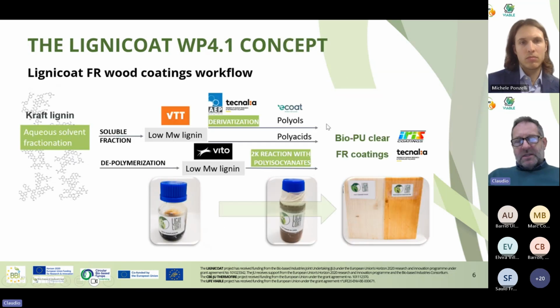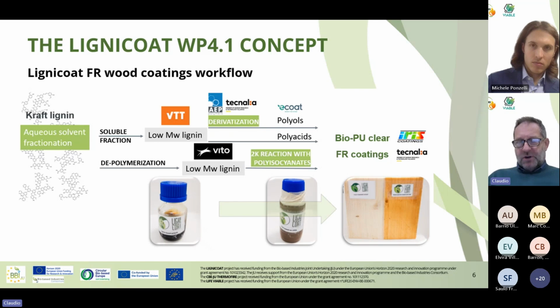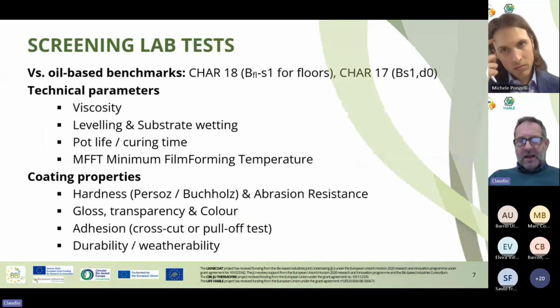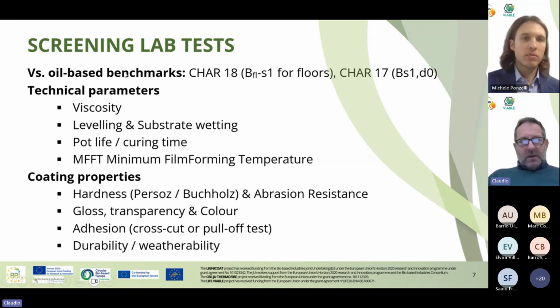Two-pack system means that lignin is included in one of the components and the isocyanate in the other, and you have two drums that will be mixed just before application, and the reaction occurs during application, and this is giving a particularly high characteristic of the coating. We have used as a reference throughout all our work two benchmarks.